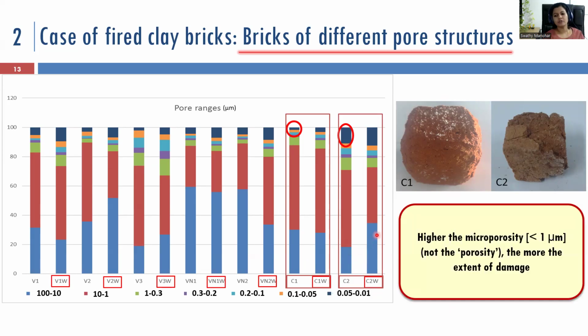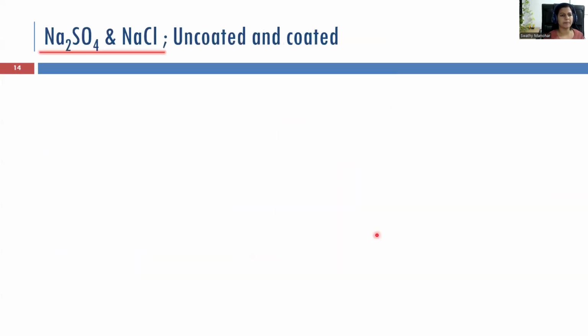The major conclusion from this slide is that if the microporosity is higher, which is pores less than 1 micrometer, the more is the susceptibility to damage. So it's not the total porosity that we should be worried about, but the percentage of microporosity in a system.